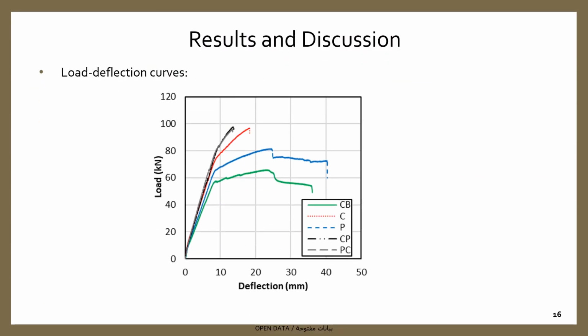In this load deflection curve, it clearly indicates that the ultimate load carrying capacity of the strengthened specimens outweighed the control beam, particularly the enhancement in the yield and ultimate load compared to CB. Specimens C, CP, and PC provided similar strength improvement, while specimen P displayed inferior capacity than CFRP strengthened beams. This is due to the significantly higher tensile capacity of CFRP compared to PET-FRP laminates, which resulted in better performance in terms of load carrying capacity.